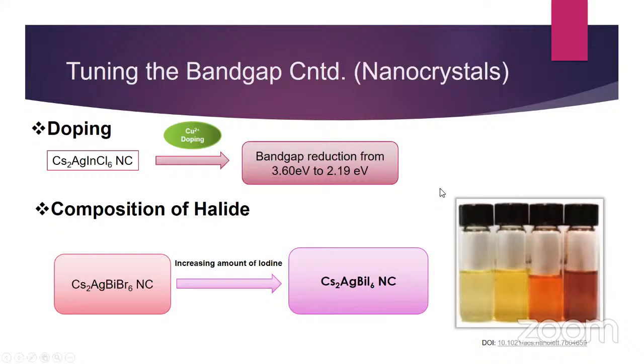And yes, you can also tune the band gap of the nanocrystals. So basically by doping this Cu2+, the band gap of Cs2AgInCl6 can be reduced from 3 electron volt to 2 electron volt. And also you can change the composition of halide to tune the band gap.